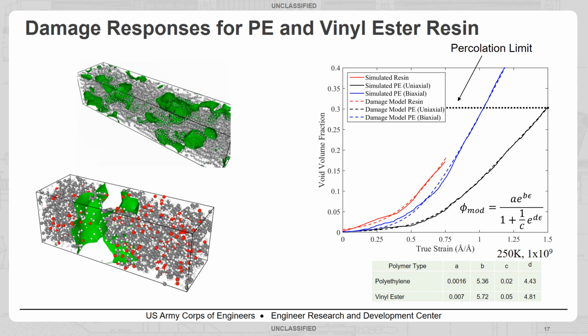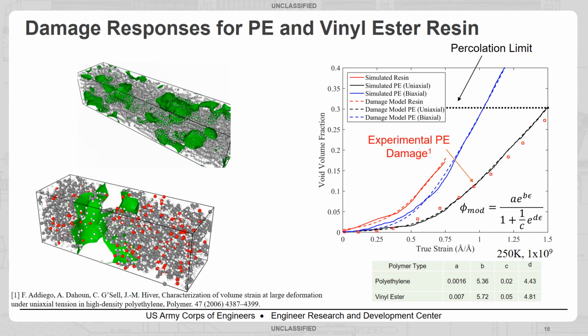Here we have our coefficients. So we see that this damage model that we developed captures this nanoscale damage evolution with pretty high accuracy. So next we want to compare our simulated void volume response to some experimental work done by G'Sell on characterizing the volume strain of high density polyethylene. So we see here that our uniaxial simulated results do a very good job at capturing the uniaxial experiment void volume evolution here in these red dots.